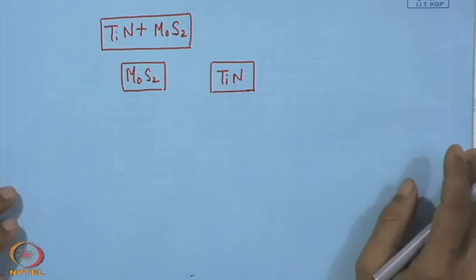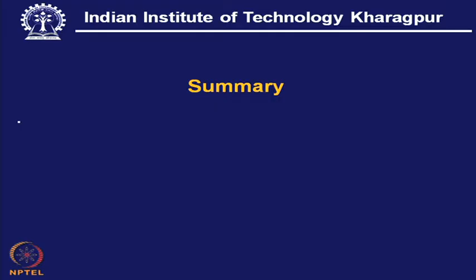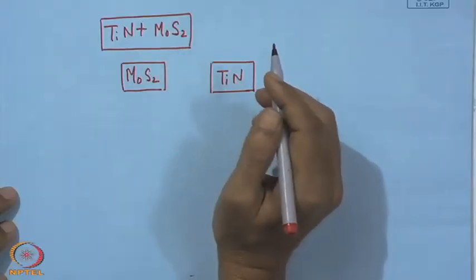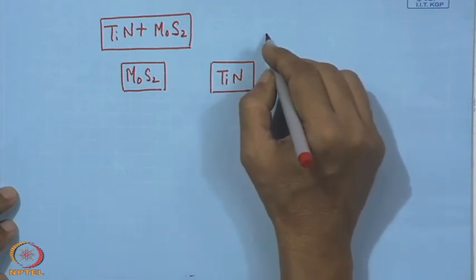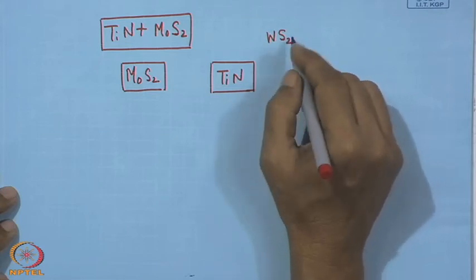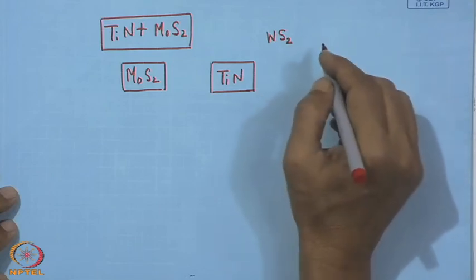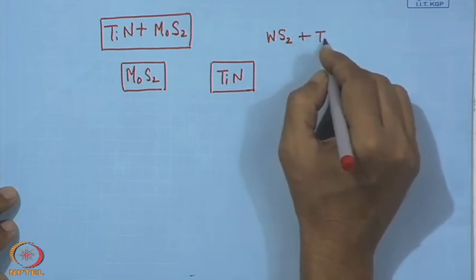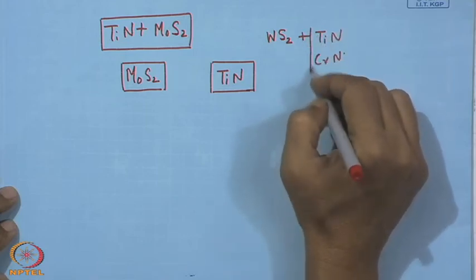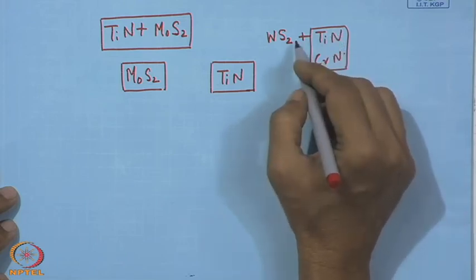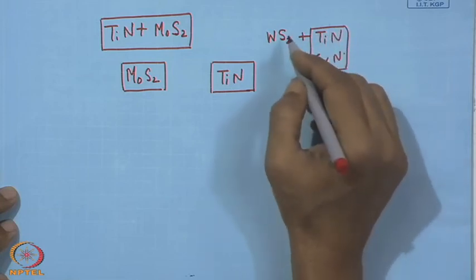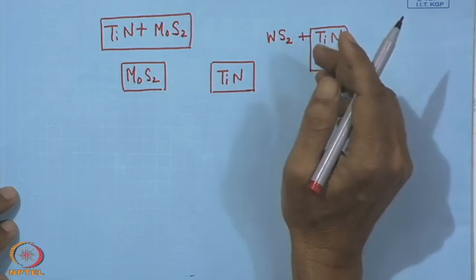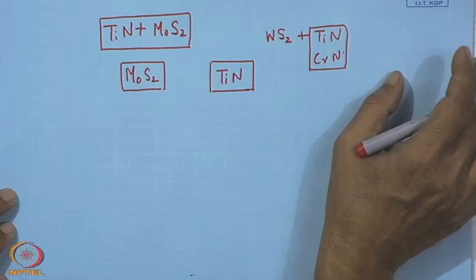So, one has to look to this, and by this also what we can see that it is MoS2, but similar effort can be also made with other coating material, say for example WS2 with some of the hard coating from this hard coating family, and it can be titanium nitride or chromium nitride or some of this. So, that can be also useful to augment this property. That means, it is the hardness on one side and also the wear resistance on the other side. So, these are the coating architecture which are of immediate interest and immediate use, and these are the materials also need proper evaluation.